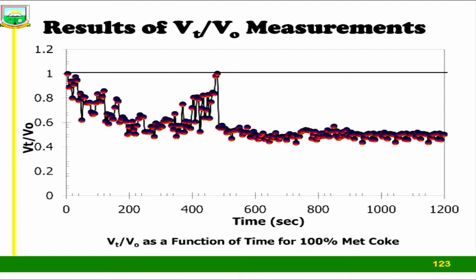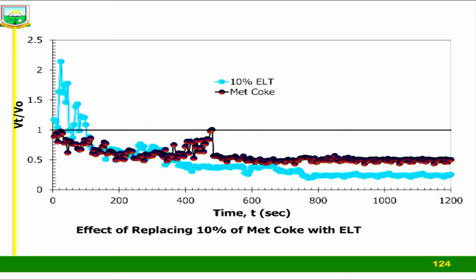You see that they will hardly have any foaming. Then what happened? We replaced part of the coke with 10% vehicle tire. Especially at the beginning, because of the volatile nature of the reaction when you have vehicle tires, we're able to have about 2 minutes of foaming. And trust me, with 2 minutes of foaming you can gain more than about 5 billion every year. Just 2 minutes of foaming.